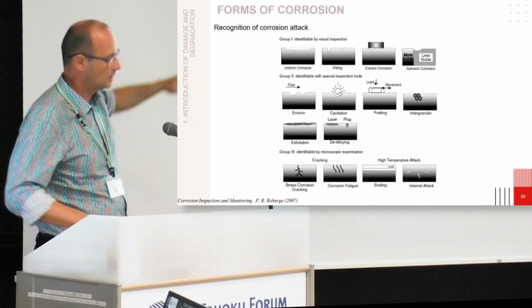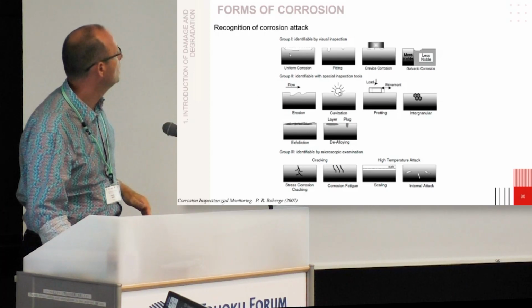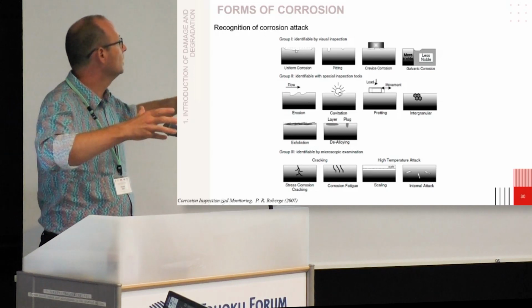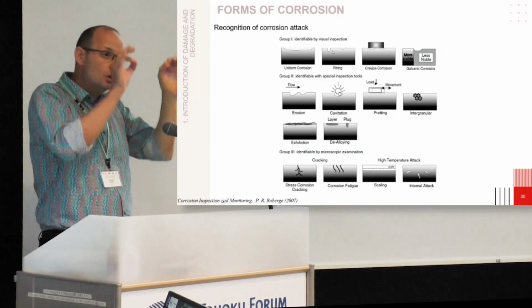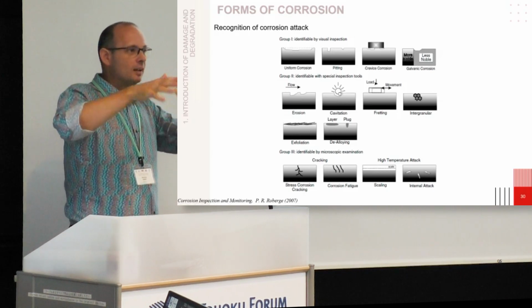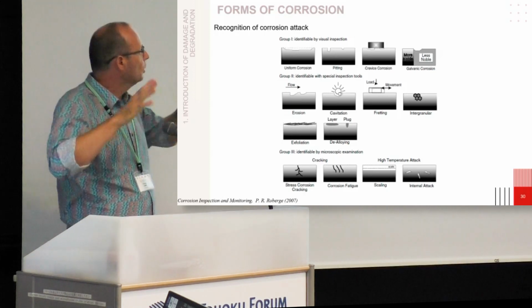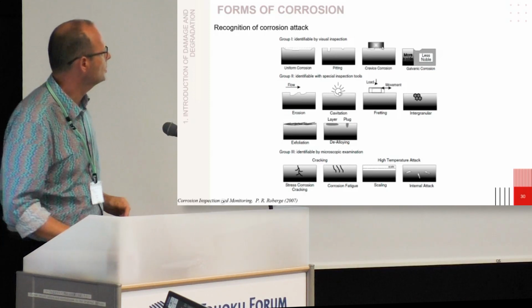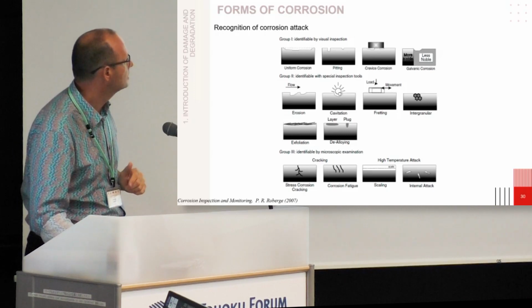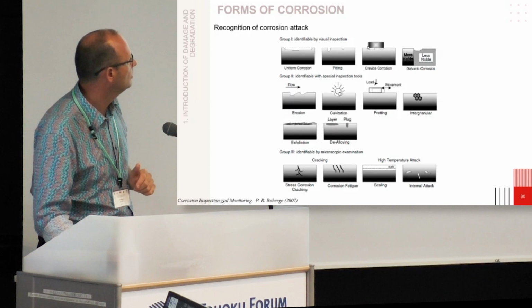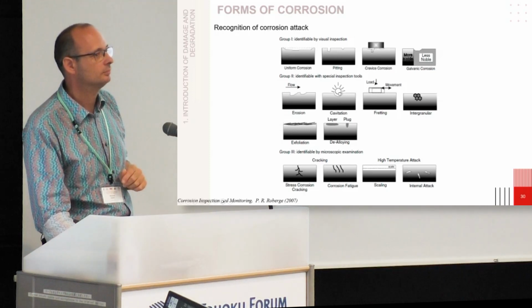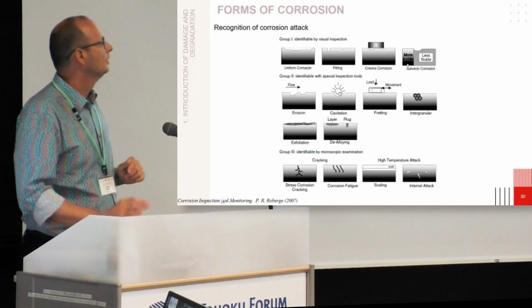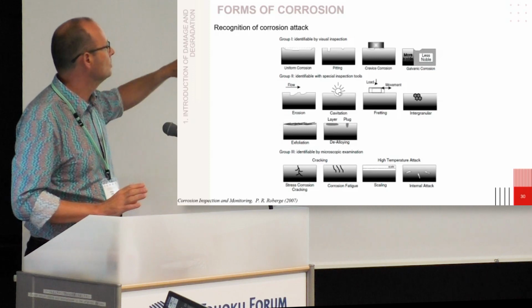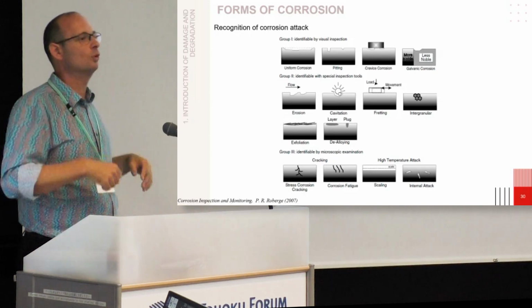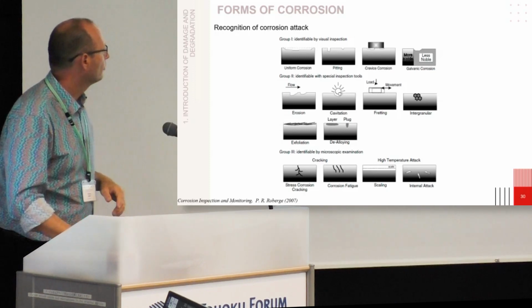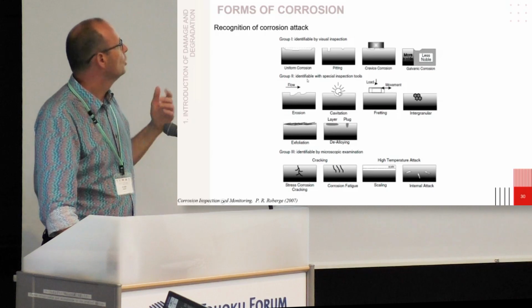So you have a drawing here and you can see that, yeah, you will have a depth created. Pitting, so it's a local dissolution of the material. Sometimes it's not so easy to observe, but you can. Crevice corrosion. So crevice corrosion, I will give a small detail about that, but it's clearly when you put pieces together and actually the material will dissolve under the pieces. Or galvanic corrosion, that's a funny type of corrosion I will show you. It's because one material is protected and the other one dissolves. So it's very easy.